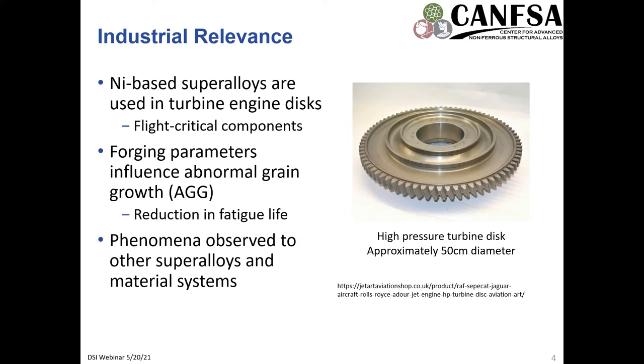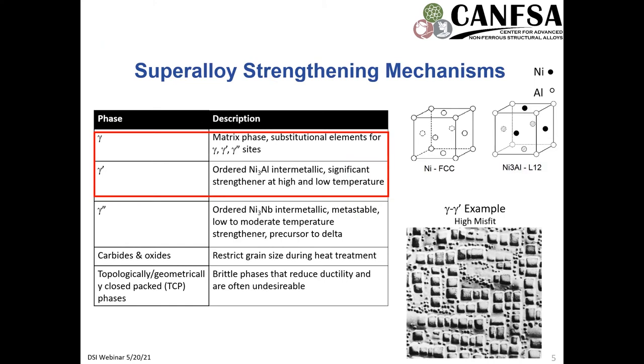And as we've discussed, the forging parameters, particularly during isothermal forging, can cause abnormal grain growth, and it can occur at various stages throughout the processing. And this is observed not only in this alloy system, but other superalloy system materials as well. There are different mechanisms by which abnormal grain growth can occur, and we're going to be trying to focus mostly on this material system. So within this alloy and alloy system that we're utilizing, there are two phases that we're mostly going to be talking about. One is the gamma and the other is the gamma prime.